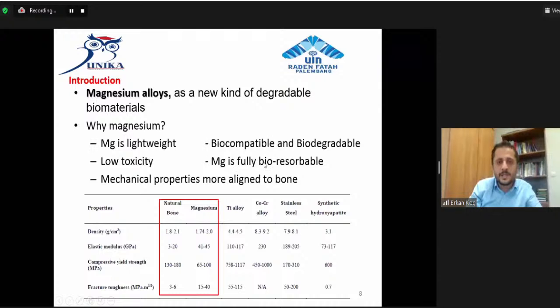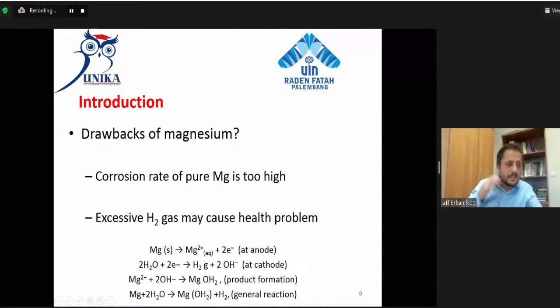Magnesium is fully bioresorbable. However, magnesium has some drawbacks. It degrades too quickly in physiological systems with a pH level between 7.4 and 7.6 and high chloride concentration. Then the implant will lose its mechanical integrity because of fast corrosion. It will lose its mechanical integrity before the tissues sufficiently heal, and the host tissue cannot deal with too much hydrogen generated from the corrosion process, as shown here.